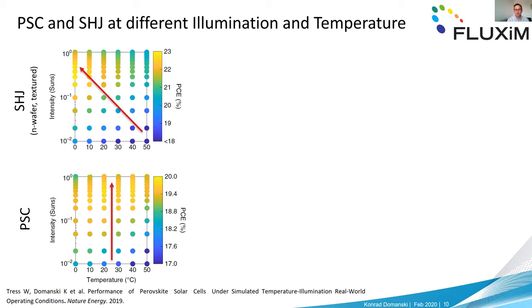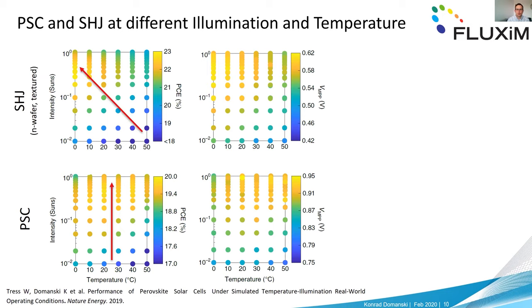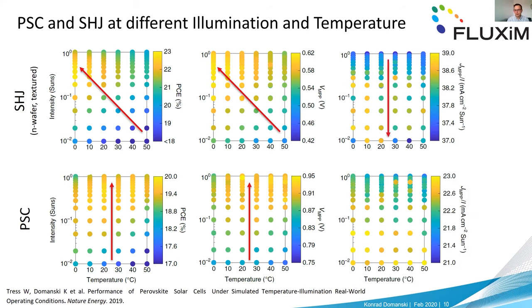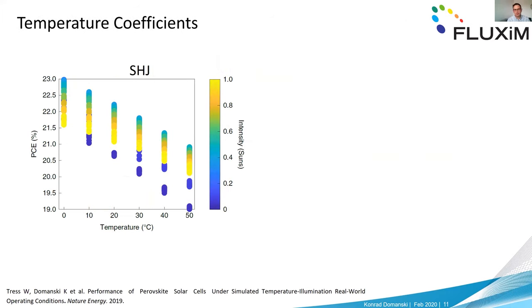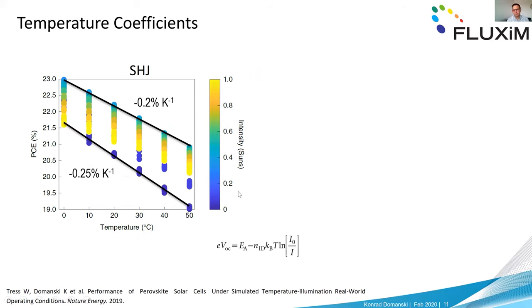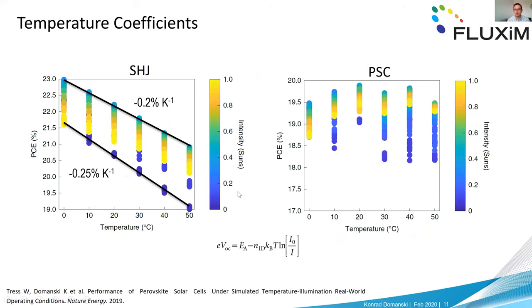For silicon, best performance is at low temperature and high light intensity. For perovskites, there's not much temperature trend but performance is better at higher light intensities. At MPP, voltage trends for both silicon and perovskite follow the same trend as efficiency. The fact that they behave similarly is important because many argue the path of least resistance to market for perovskites is to pair them with silicon in a two-terminal tandem — it's important that currents remain matched across temperature and illumination.